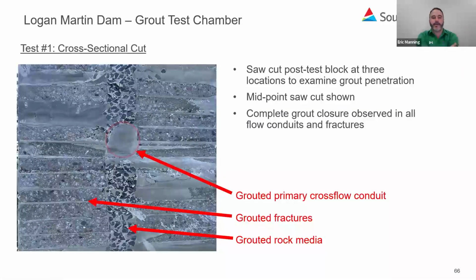As you can see, the first set of tests that we performed went really well. This is a cross section, a cut section through the test chamber after the test had been completed and the grout set. We were able to achieve pressure in the chamber, grouting off the conduit pretty effectively. This was grouted off with a 1-to-1 high mobility mix. You can say it was pretty effective.